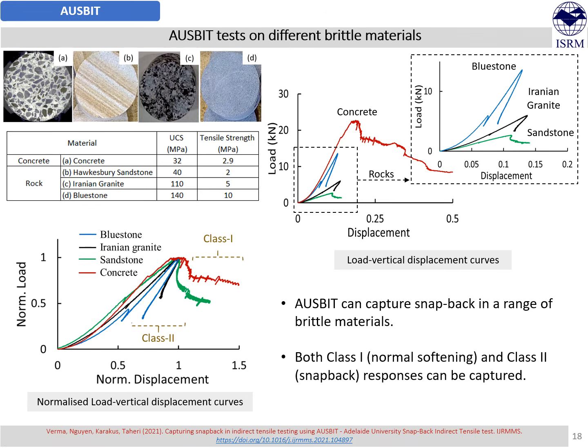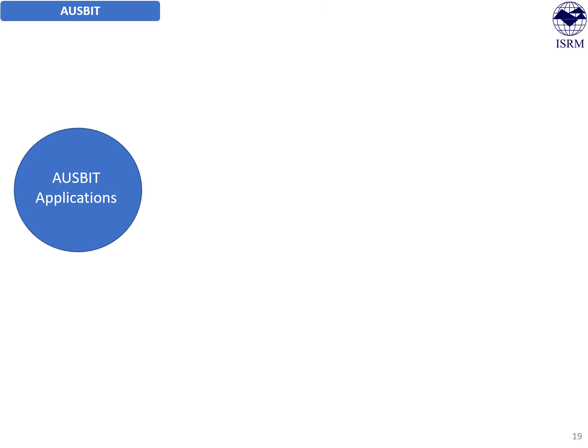Now from the normalized load versus displacement response, we can see that concrete, on one hand, performs class 1 response in terms of its post-peak behavior, whereas brittle materials like rock demonstrate class 2 behavior. These class 1 and class 2 behaviors were both successfully captured by AUSBIT experimentation, which was not possible earlier in the conventional approach. Now, yes, AUSBIT can capture the true post-peak behavior of a disk specimen under diametrical cracking.